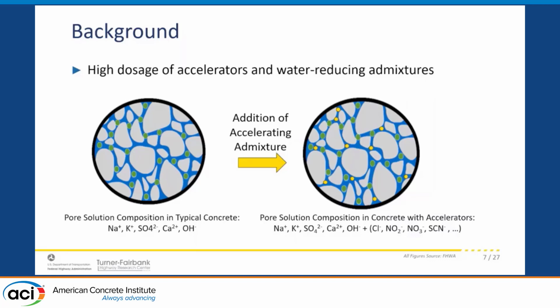One of the things we thought about is using electrical tests. Electrical tests are fairly rapid, and they give us very useful information on the transport properties of our concrete. Transport properties are important because they basically determine how much fluid the concrete absorbs and how fast ions can travel through the concrete. We all know that durability of the concrete is influenced by things like freeze-thaw performance or by corrosion resistance, and we know that corrosion is driven by chloride ions or carbonation. So these transport properties are important if we see that these mixtures are failing too early.